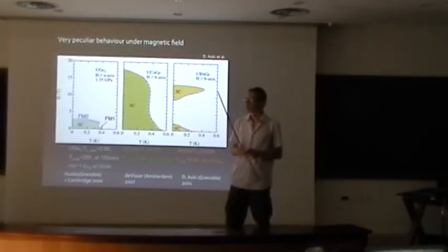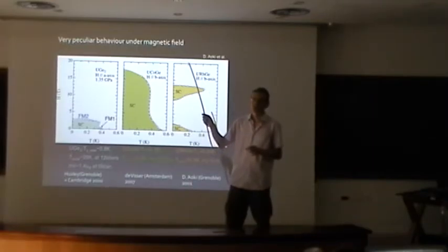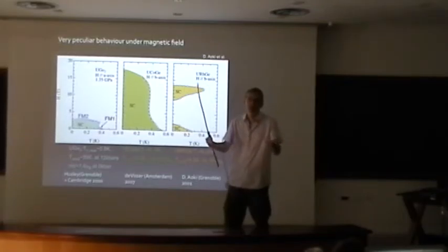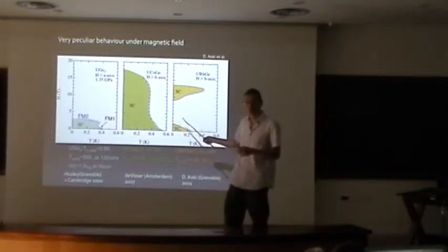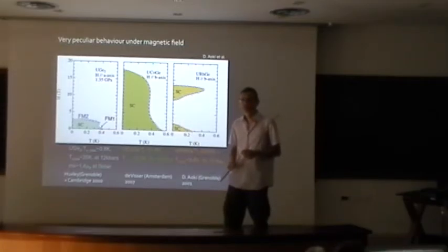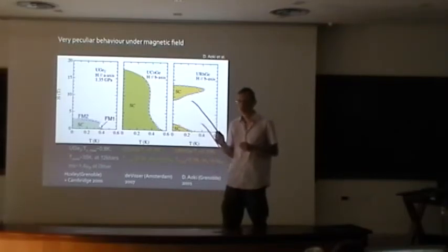For example, take solid helium-3: at high temperature you measure ferromagnetic correlations, and it orders antiferromagnetically, so both orders are usually competing. It's true also for these compounds. So can we conclude that antiferromagnetic fluctuation is not universally the origin of superconductivity in heavy fermions? Seems so, yeah. People are also looking at mechanisms like valence fluctuations to induce superconductivity, as well as antiferromagnetic and ferromagnetic fluctuations.